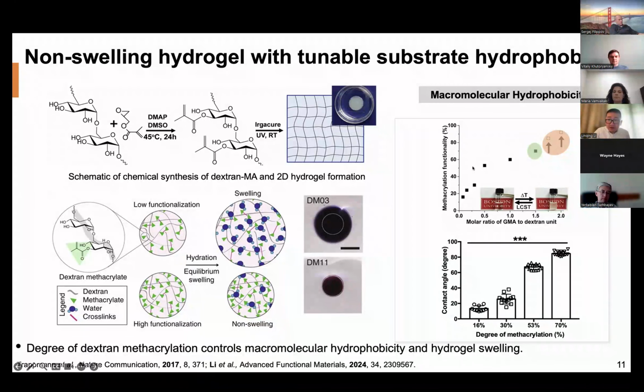From the figure here, we are able to achieve high modification. See the yellow, orange, and light green circles. This is 70% modification, which we found is a threshold. Below 70%, the dextran solution dissolves without phase separation, but once you go higher than 70% modification, you can trigger a liquid-liquid phase separation at room temperature. For the first part of the talk, I'm going to focus on everything below 70%.